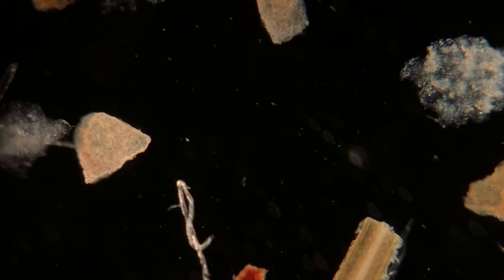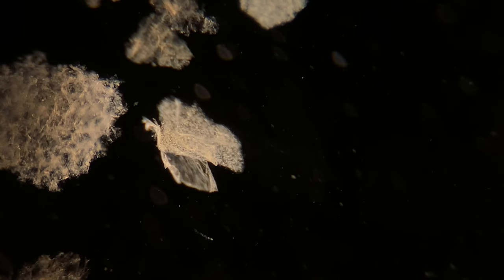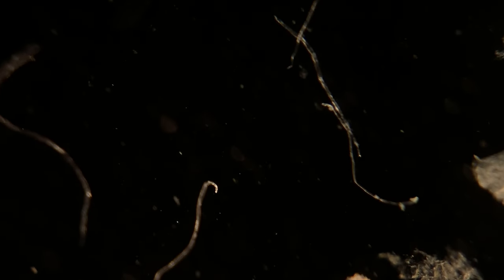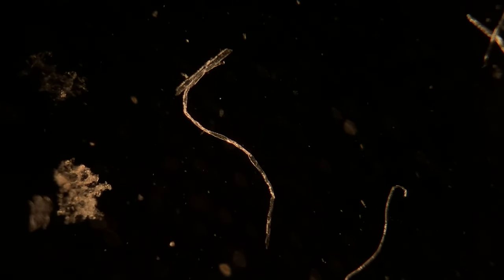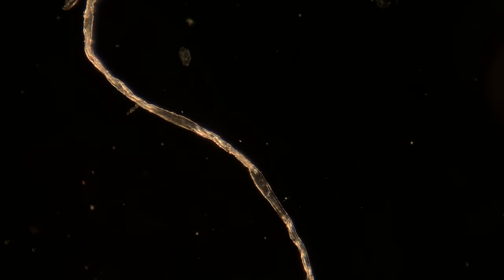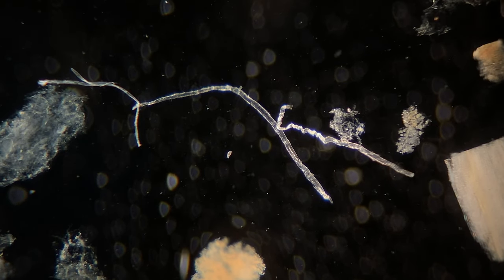This is kind of just citizen science level stuff. I don't have an infrared microscope — with infrared spectroscopy, we'd be able to shine infrared light at all of these particles, and the plastic ones give off a certain light signature reflection. Another way to identify plastic under the microscope is with a special dye called Nile Red, kind of like the YouTube channel. Essentially it adheres to the plastics but doesn't adhere to other organic material. If I had that dye, I would put it in the sample and then use a fluorescence microscope, which would make the plastic glow — that way you'd be able to see which stuff is plastic and which stuff isn't.